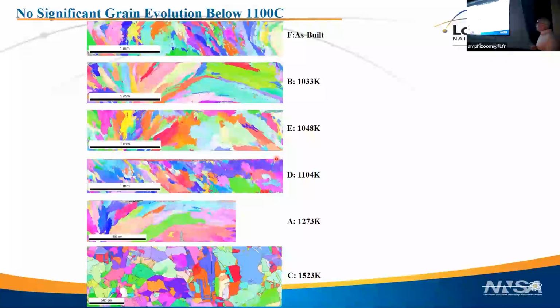Some of the things that we can't see in neutron diffraction or X-ray, well, parts of X-ray diffraction can see grain structure, but in powder diffraction, you can't see how the grain morphology changes. So this is after the heat treatment. We do EBSD, and you can see that after the highest heat treatment, you get complete recrystallization of the grains. Until then, here is kind of arguable, but there's not a huge change of the grain structure until heat treatments in excess of 1,000 degrees C.